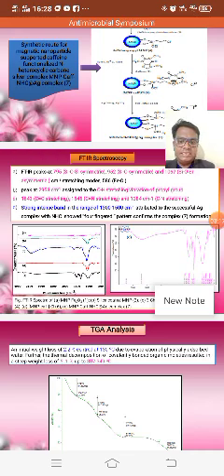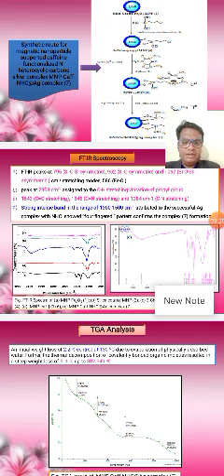nanoparticles. This complex was then characterized using several techniques such as FTIR spectroscopy. Here, the comparison of the FTIR spectra of the bare magnetic nanoparticles, the precursor and the final product shows changes in the peak pattern in the FTIR spectra. So it suggests the formation of the caffeine-based N-heterocyclic carbene complex on magnetic nanoparticles.